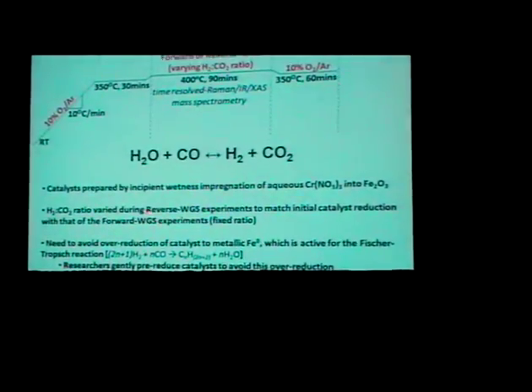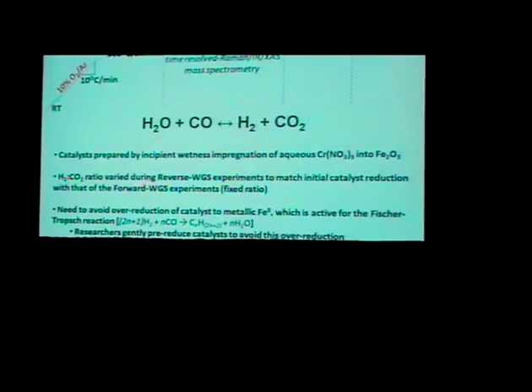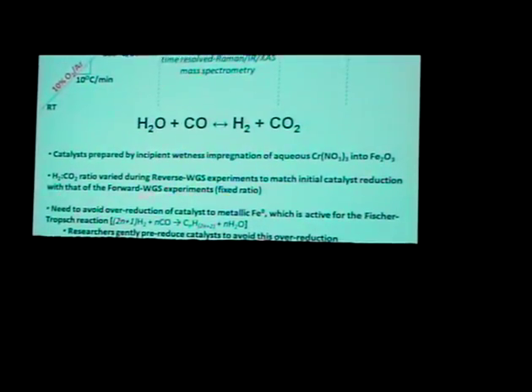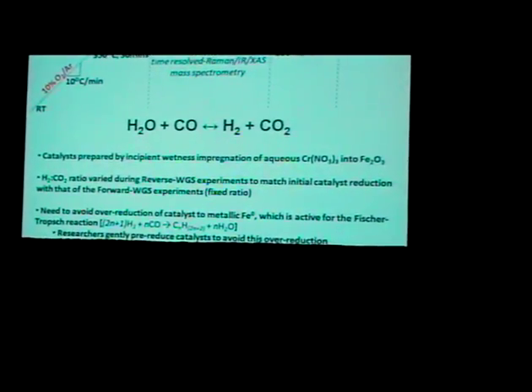So the way the catalysts were prepared was by incipient wetness impregnation of chromium nitrate aqueous solution into iron oxide powder, and we varied, as you'll see, the H2/CO2 ratios or the H2O ratios to match the initial catalyst reduction that you find also in the forward water gas shift experiments. And so we looked at various compositions.